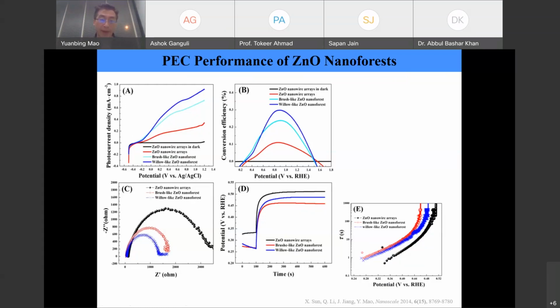So here we look at these three samples again under the solar light. And then we also compared with the sample which is in dark. So that's why you see four curves here. In terms of the potentials, we started from -0.5 to 1.2 volts. And then you will see that definitely the willow-like zinc oxide nanoforest has the highest photocurrent density.